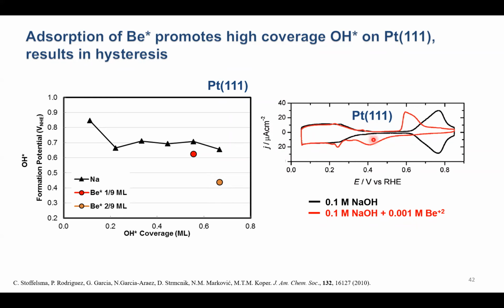to very low potential. And so we wanted to investigate this further, trying to determine if this is really what was going on. I think any experimentalist would look at this CV and say, this peak splitting is due to kinetics, not thermodynamics. Typically, when we see a hysteresis or a peak splitting in an adsorption peak between the positive and negative going scans, our first thought is that that corresponds to slow kinetics. Basically, we're scanning the potential at a faster rate than the rate of our reaction. And so we're not really giving the reaction enough time for the species to adsorb and desorb. If we slowed down the scan rate, these two peaks would come together.